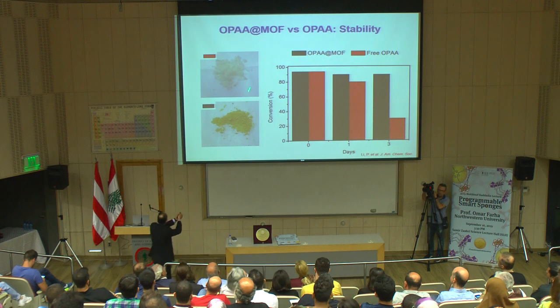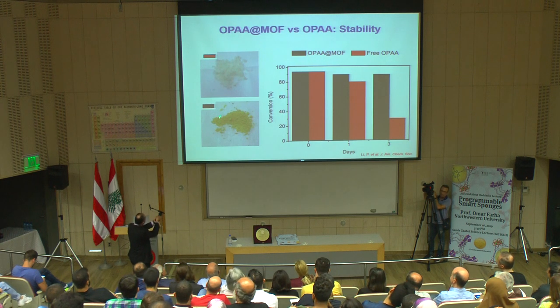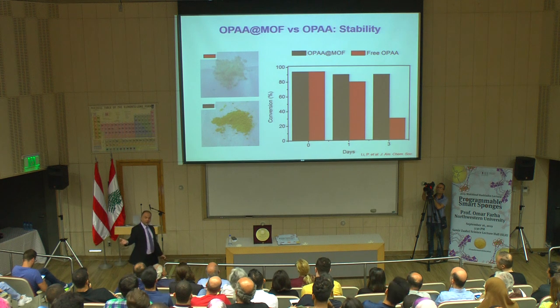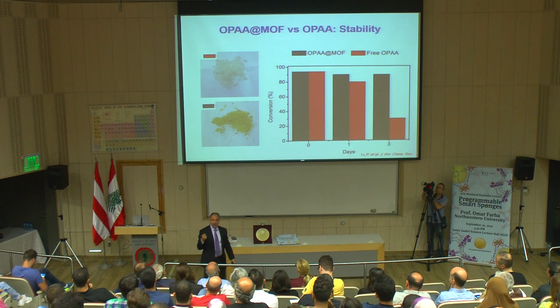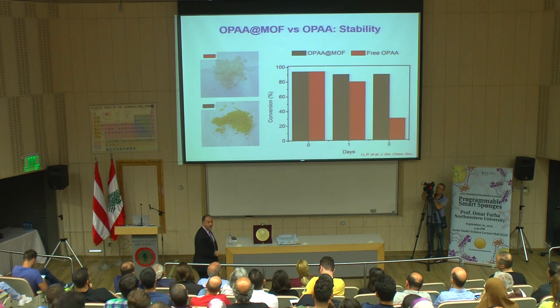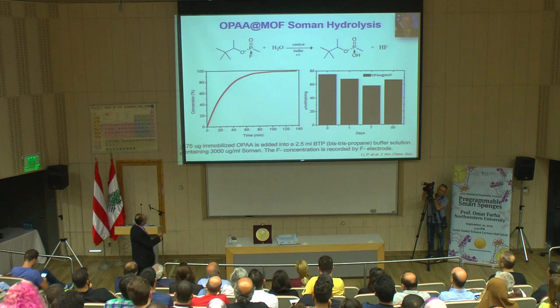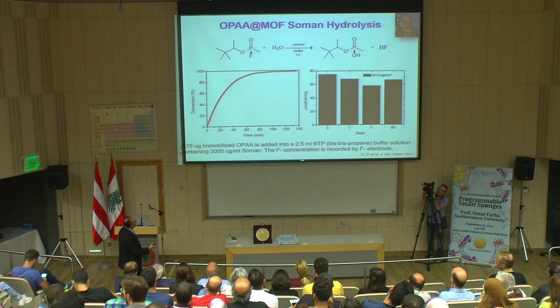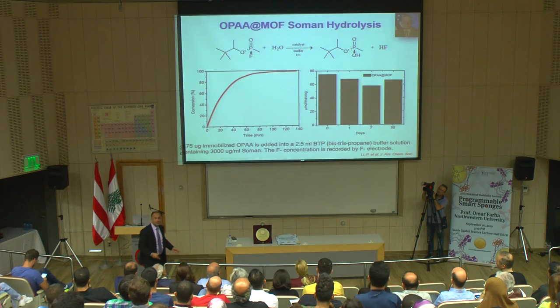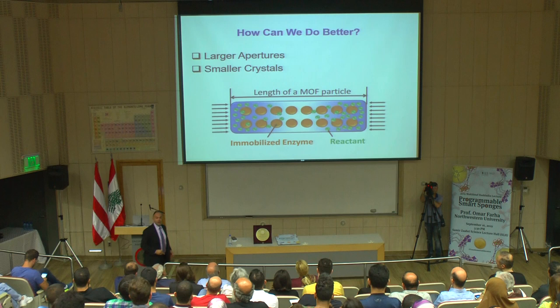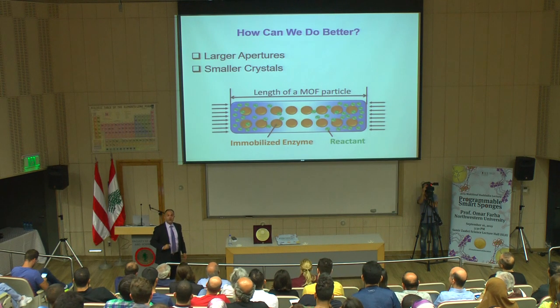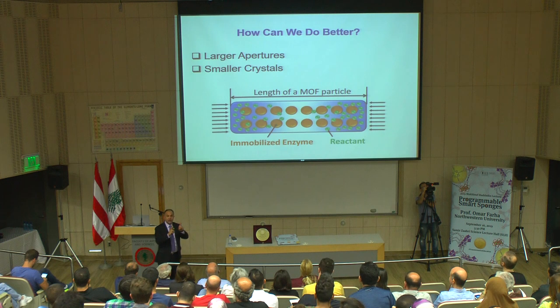The way to do it, you take the enzyme and you lyophilize it, or you take our composite and you dry it, you put it on the bench at room temperature, and every day take a small amount and do the catalysis. By day four, the free enzyme is completely dead versus our composite, nothing happened. You could even test it with harsher chemical toxins, and day zero and day 50 all the way to 6 months, this material does not change. But now we have to address that problem with the initial rate, that the free enzyme is much faster. How do you go about that?